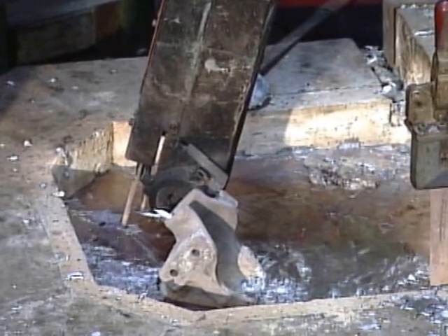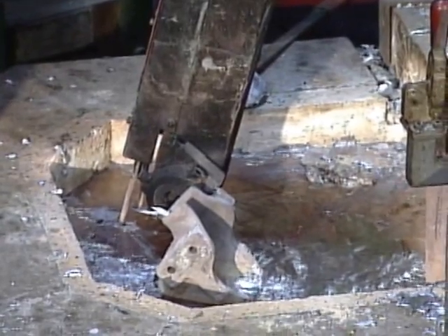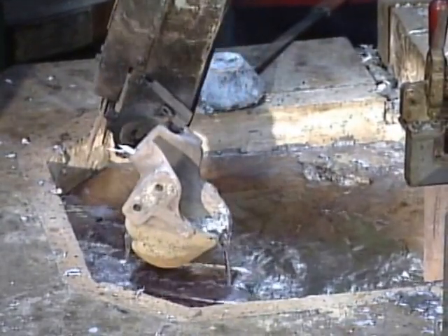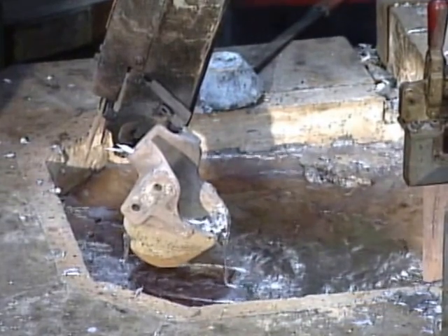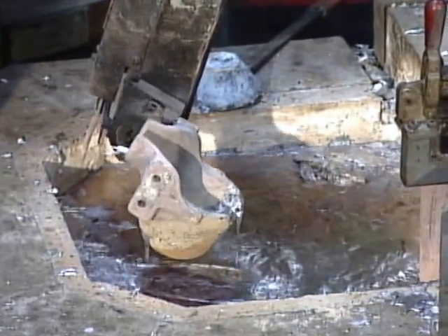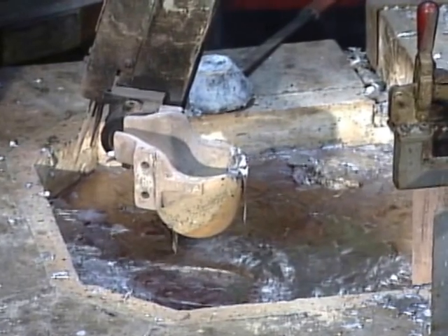The ladle may also have a timer that keeps the dipper in the metal while filling. Too much time in the metal can increase the cycle time. But be careful. Incompletely filling the dipper can cause inconsistent shot size.